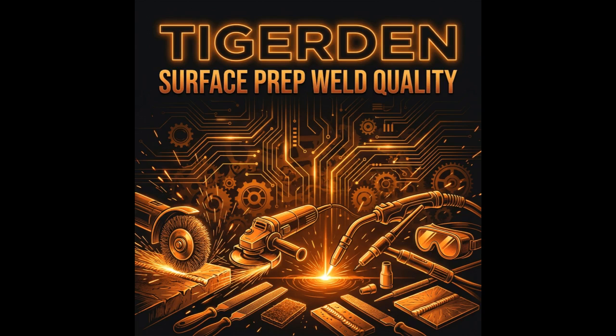I've seen some people use those flap discs too. They seem friendlier, less like they're trying to kick back and take your thumb off. The flap disc is the artisan's choice for cleaning. A Type 29 flap disc is great because it has that slight angle. It lets you get in there and buff away the surface contaminants without being quite as aggressive as a hard rock wheel. It leaves a finish that's ready for a first-class weld. But remember, cleaning isn't just about the top. You have to clean the edges, the back, and about an inch away from the joint on all sides.